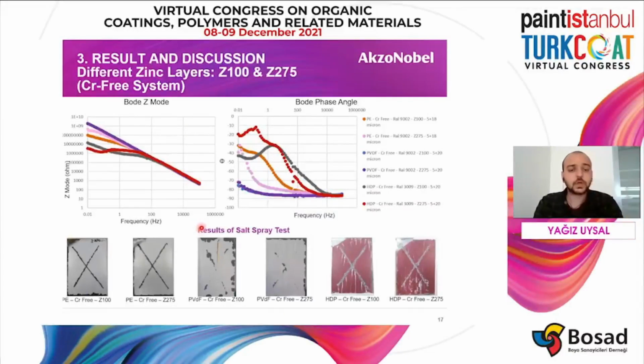And we can continue with the comparison of different zinc layers. Again, here we have 3 kinds of resin, polyester, PVDF, and high durable polyester, and we have 2 different zinc layer amounts, 100 and 275 grams, so it makes 6 different data sets. And in the Bode impedance graph, we can actually see 5 of them. Actually, this is not 5. The highest one, the purple one, corresponds to 2 of the PVDF coatings. I mean, the 2 PVDF samples' results are overlapping in the one.